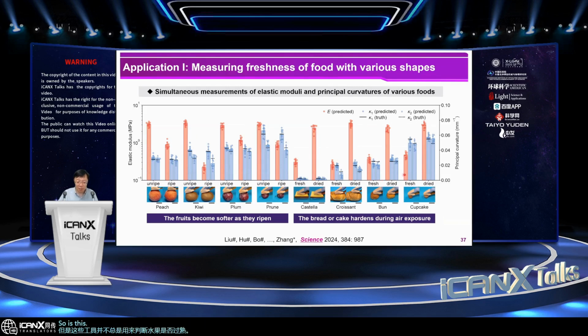So this slide shows the use of the tactile system to measure quantitatively the elastic modulus of 4 fruits, including the peach, kiwi, plum, and prune, in both unripe and ripe conditions. We have also measured quantitatively the elastic modulus of 4 fermented bread and cake in both the fresh and dried states. It's clear that the fruits become softer as they ripen, but the bread hardens during the air exposure.